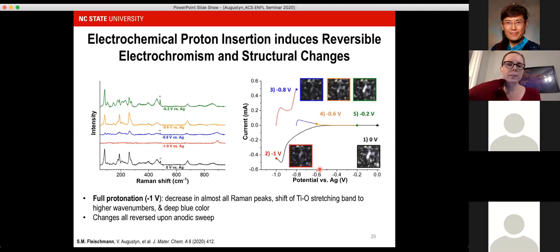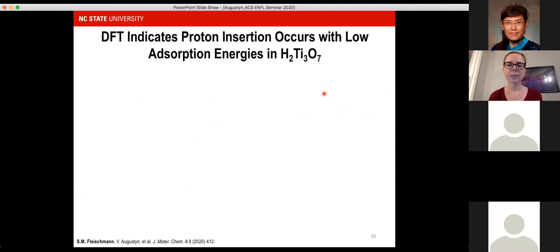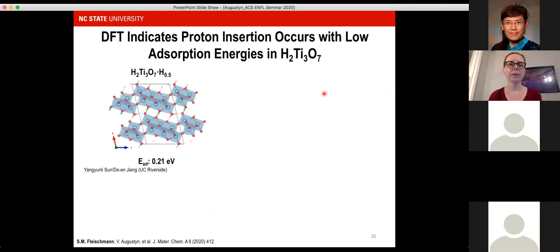We did in situ Raman spectroscopy, and it showed us that there's reversible structural changes that are taking place as a function of the applied potential, as well as a very strong blue electrochromism. All of these are indicative of a bulk insertion process taking place into the materials. To help us understand, in this case, why we saw this very strong dependence on the degree of structural protonation, we turned to density functional theory through our collaborators at UC Riverside and found that in the H2Ti3O7, the adsorption energy for electrochemically inserted protons is fairly low, and it's accompanied by an interlayer contraction. That's how the structure accommodates the excess protons.